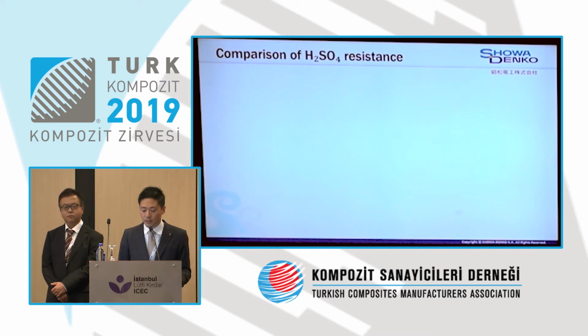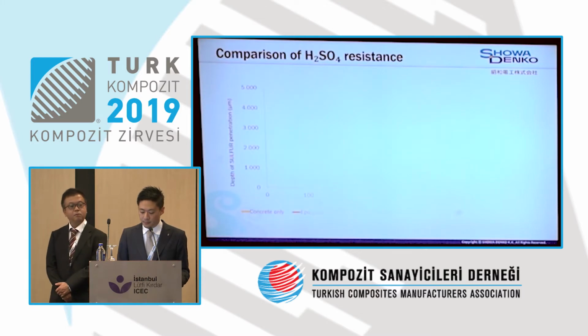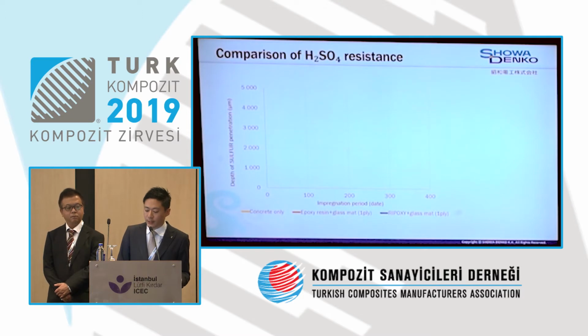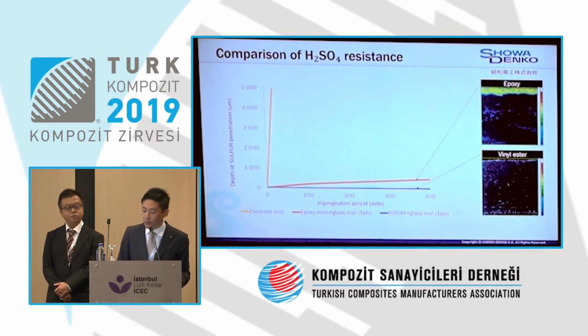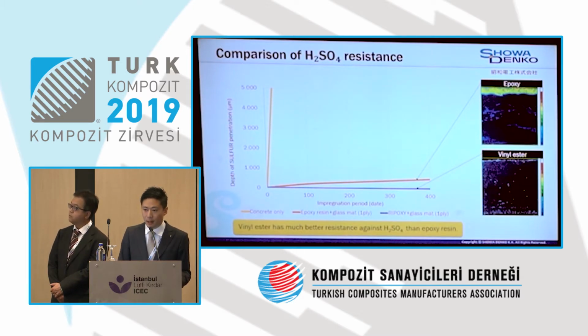As an example of corrosion resistance properties, I will show you a sulfuric acid immersion test result. Penetration depth from sulfuric acid is set on the left-hand axis of ordinate, while the immersion date is set on the right-hand axis of ordinate. Basically, concrete is easily affected by sulfuric acid, like this. If you apply epoxy on it, it will be protected to some extent. If you apply VINYLESTER resin on it, sulfuric acid has little effect on it. It shows vinyl ester has much better resistance against sulfuric acid than epoxy resin.